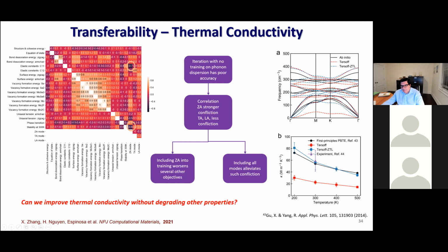And that translates into a very poor behavior of the thermal conductivity as a function of temperature when you compare with DFT data. And the question is then, can we use this methodology to improve the parameterization without degrading other properties? Because of course, you can always improve for selected properties. And this correlation metrics helps to understand one key concept here. If you improve the out-of-plane mode, which is very important in phonon propagation, the ZA mode here, it is strongly negatively correlated with, for instance, elastic constants and stability of the atomic structure at room temperature.